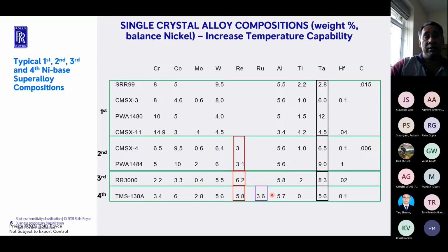So the long and the short is fourth generation alloys have now been discontinued. One of the main reasons being cost. The implications of cost are too strong to counteract anything in terms of the life of the blade. So in Rolls-Royce, our general route is that we use CMSX4 as our second generation alloy, and we use RR3000 or RR3010 as a third generation alloy. We use little to none of any of the other alloys.